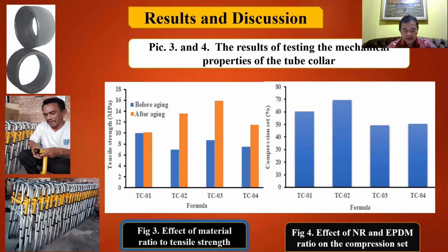For the tube collar of 4 samples, the highest value is 69.26% at TC02. Figure 4 shows that the difference in the ratio of material, natural rubber and EPDM, determines the compression set value. And other mechanical properties, Figure 1, Figure 2, and Figure 3, as well as cure characteristic of the compound.